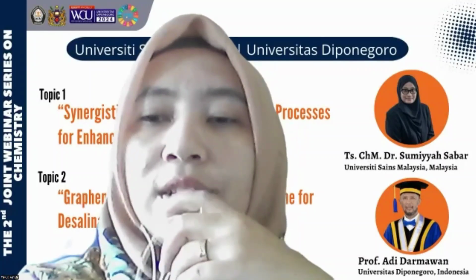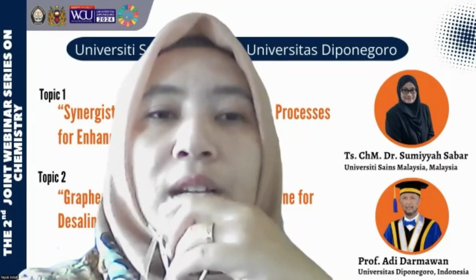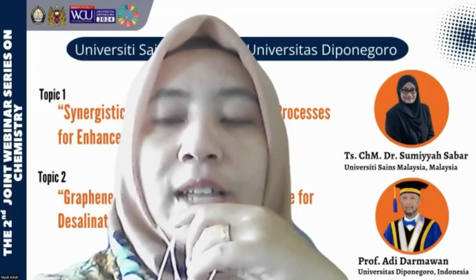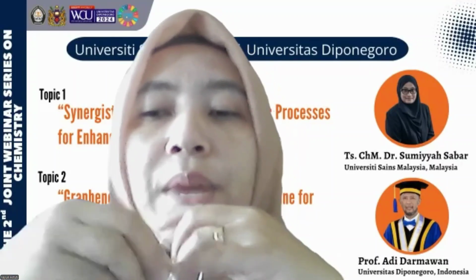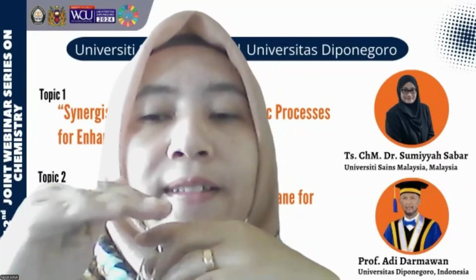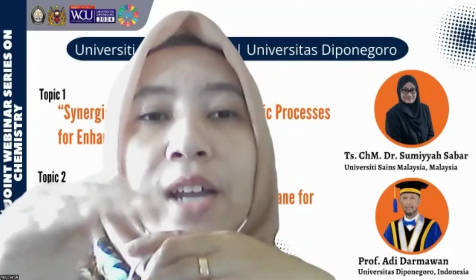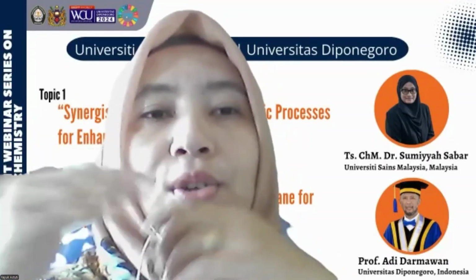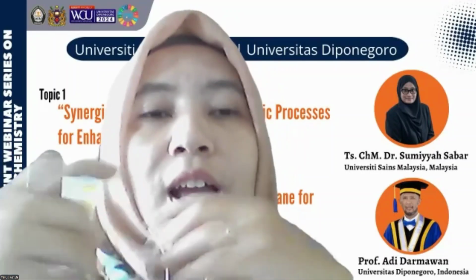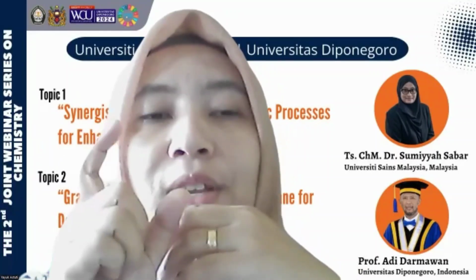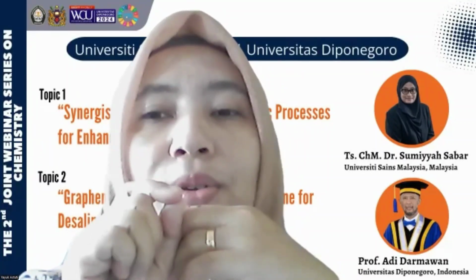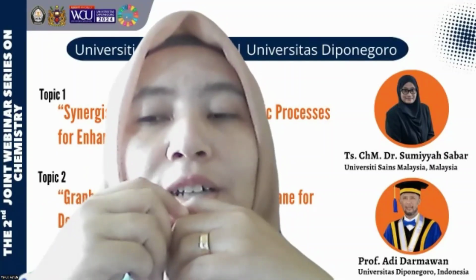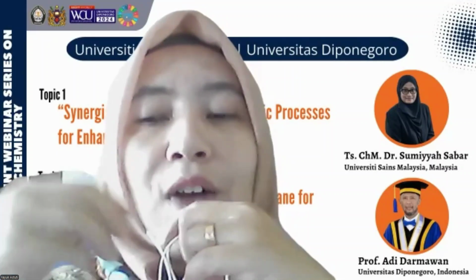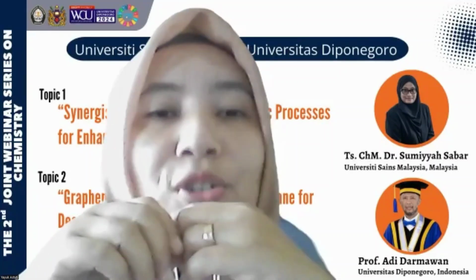How to enhance the TiO2 bond to the chitosan layer? In your presentation, you made the titanium dioxide and chitosan layer by layer: glass plate, then chitosan, and then TiO2. There should be an interaction between titanium dioxide and chitosan, so how to enhance the interaction between them, to make the TiO2 embed into the chitosan very well?